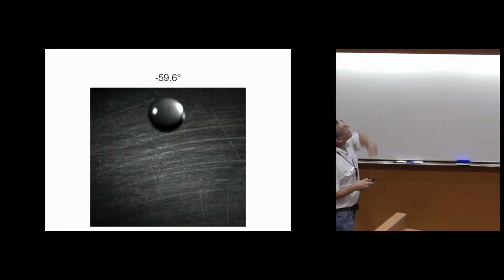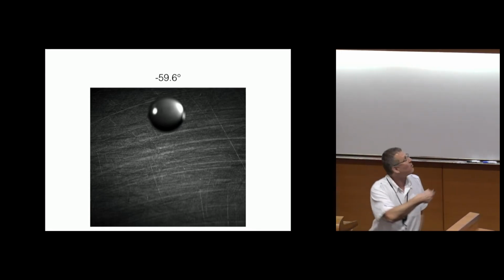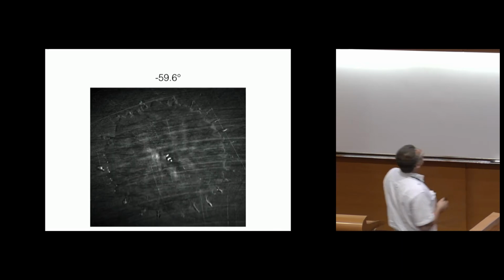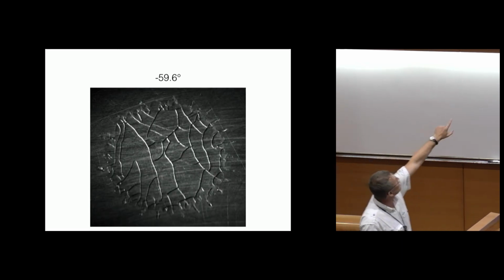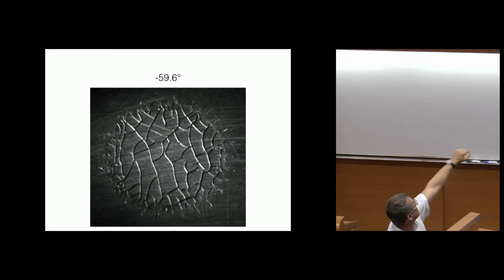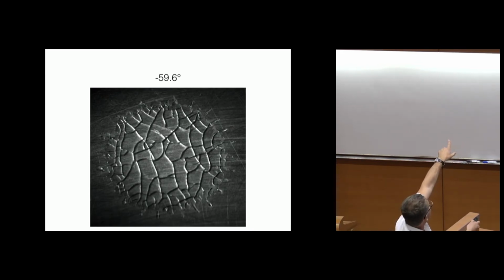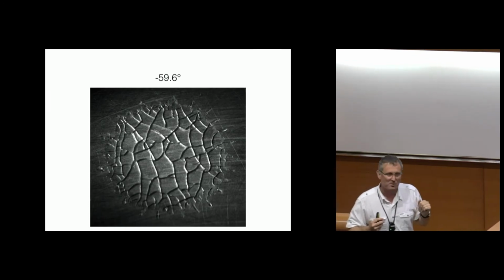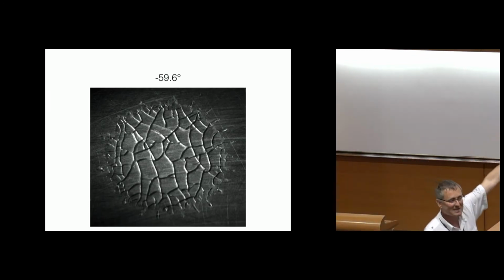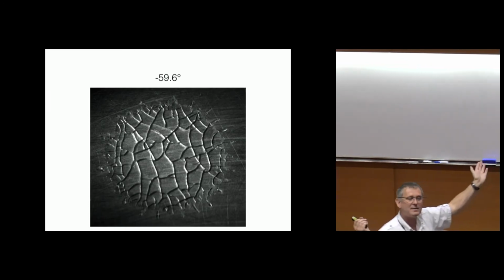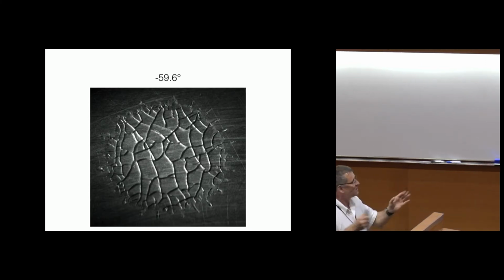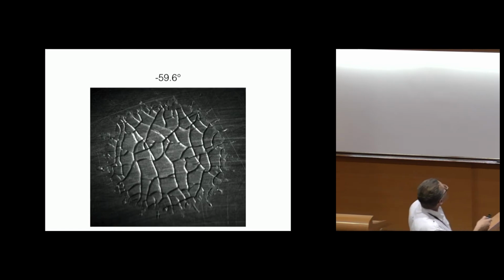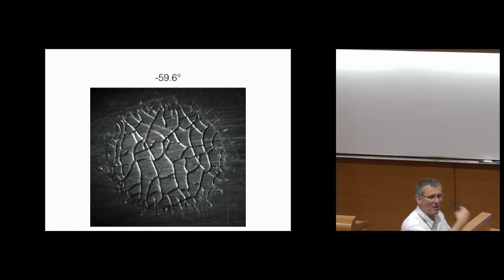Let's do it at a lower temperature, meaning a higher temperature difference. You see even something different. Now you see cracks appearing before, and now you see the retraction of the liquid. So now you see cracks appearing before the total freezing of the structure. And in that case, the cracks are quite different. Instead of having an explosion in one second, an abrupt creation of all the cracks, the cracks are created one after each other.